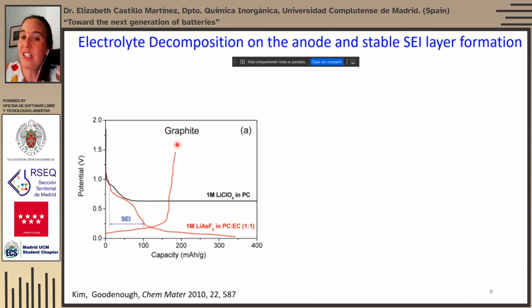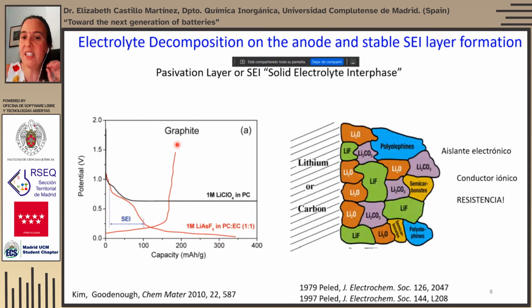So the formation of this passivation layer has become a very important issue in batteries. It depends a lot on the chemistry of the electrolyte, and it depends a lot on the chemistry of the electrode material. And depending on this, you will have a layer which has a kind of polymeric matrix with inclusions of inorganic salts. And depending on the thickness of this layer, you will have more or less resistance, because this layer must be electronically insulating, but it must be ionically conducting. So actually, the lithium ions can still go inside and outside of the electrode. So this is a very important and active area of research.